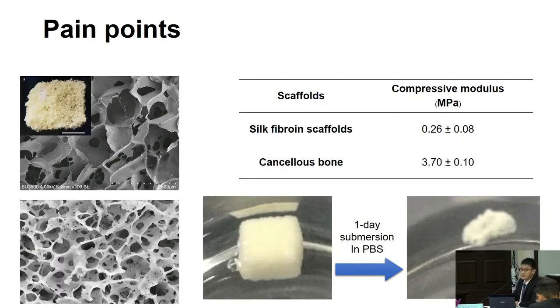But there are some problems that we need to overcome when we use silk fibroin as a bone scaffold. This is the silk fibroin bone scaffold, and when we observe the scaffold under a scanning electron microscope, we can see that it is very porous, and we have interconnected pores that allow mass transfer, for example, of oxygen and nutrients from one pore into the next pore, and that is very similar to blood transfer in the physiological condition.